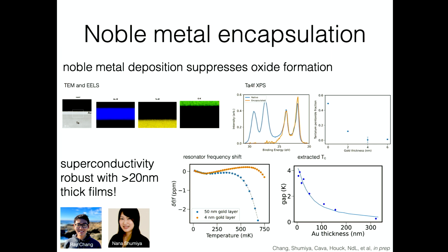So the game here is you want the noble metal layer to be thick enough that you don't form an oxide, but thin enough that you still have full proximitization. So if we put down a little bit of gold, we find that indeed we can get rid of these oxide peaks entirely with just a few nanometers of gold, which is a little bit of a surprise for me.